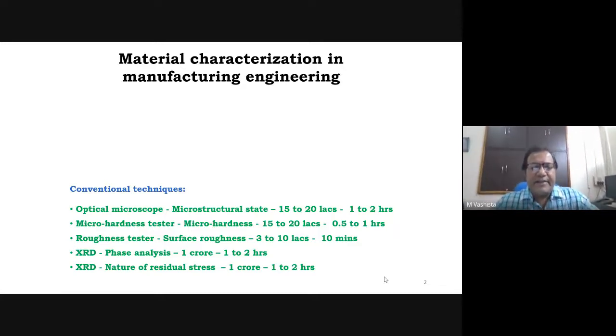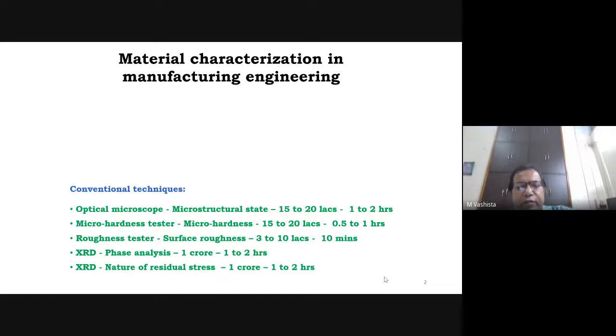Micro hardness variation can be assessed by using equipment called a micro hardness tester. This micro hardness tester also costs around 15 to 20 lakh, and the time taken will be 30 minutes to 1 hour.